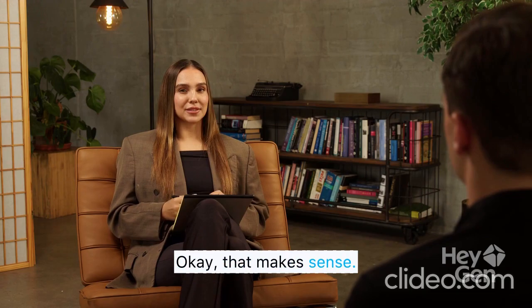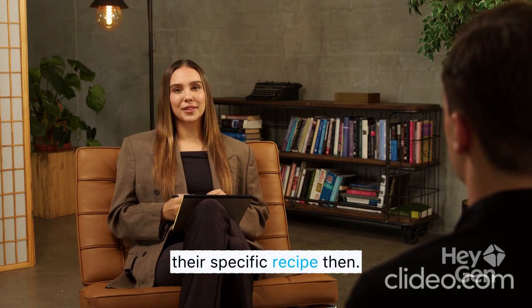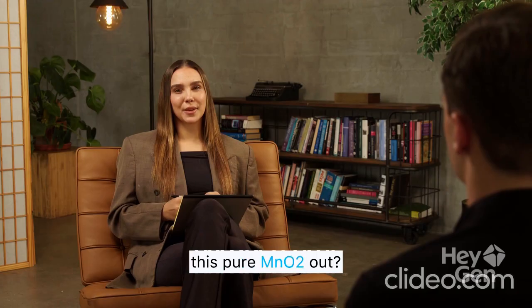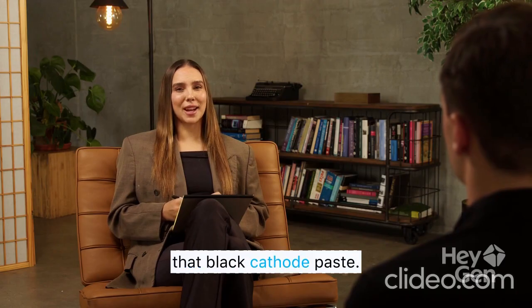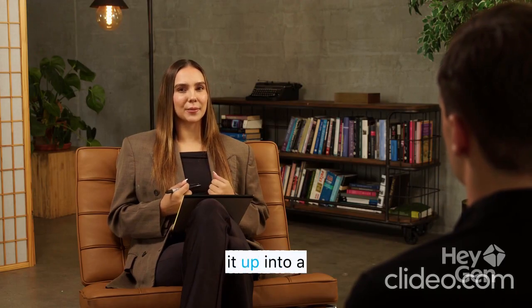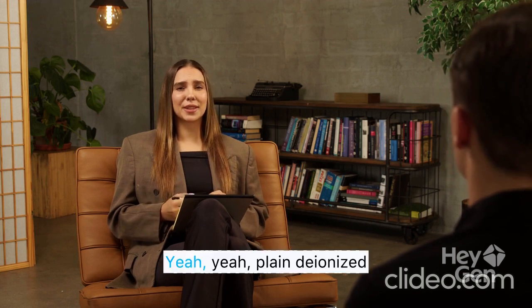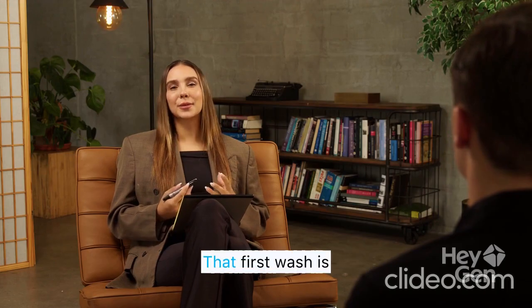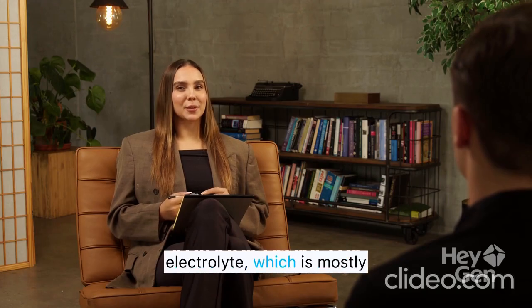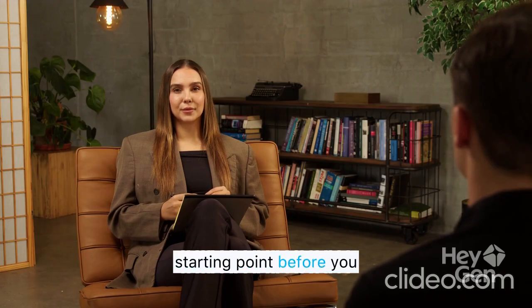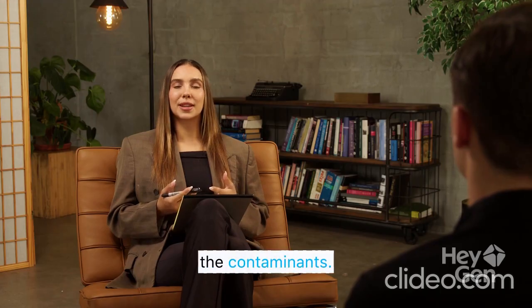Okay, that makes sense. So let's walk through their specific recipe then. How did they get this pure MnO2 out? Right, first they collect that black cathode paste. They dry it, grind it up into a powder, and then give it a good rinse. Just with water? Yeah, plain deionized water. That first wash is really crucial, actually. It flushes out leftover electrolyte, which is mostly ammonium chloride. You need a clean starting point before you bring in the stronger chemicals. Right, get rid of the contaminants.